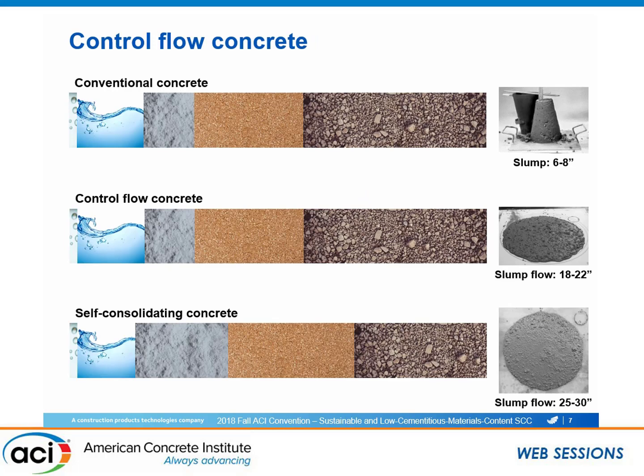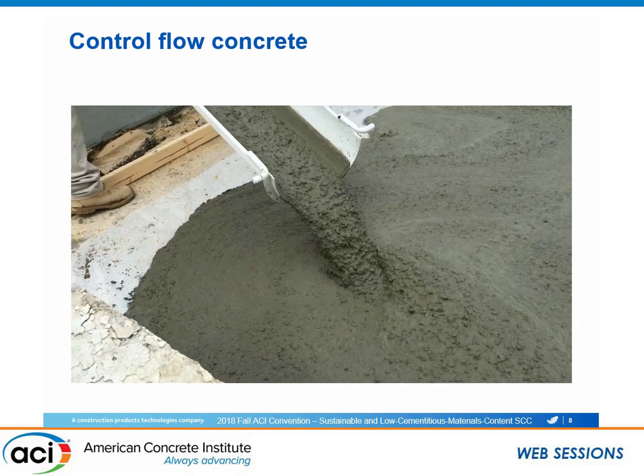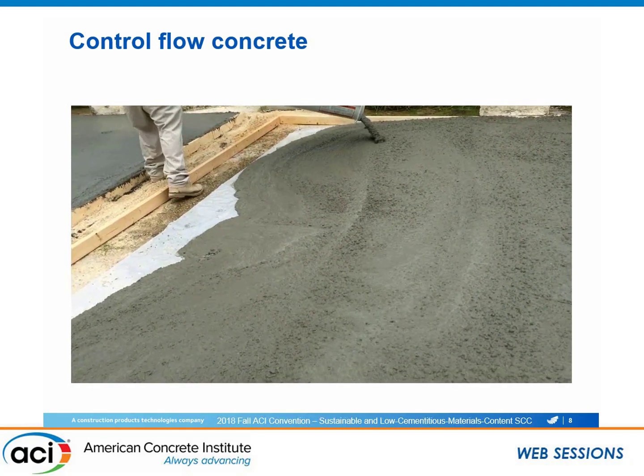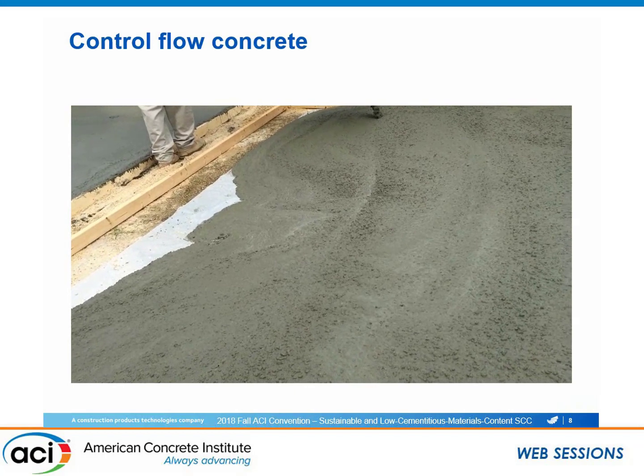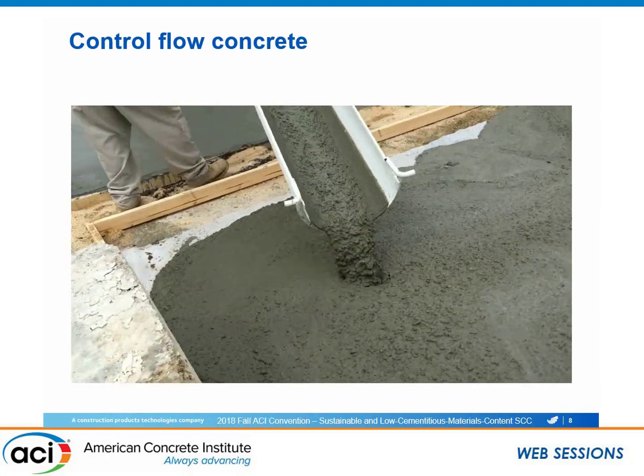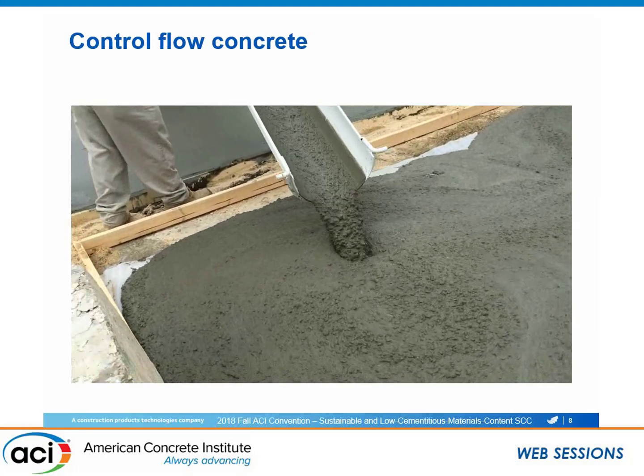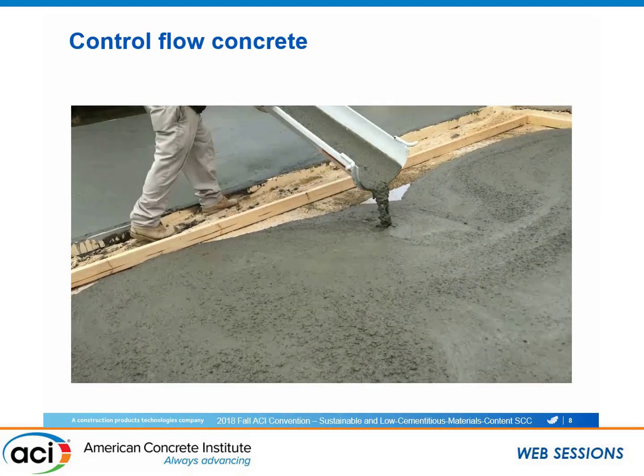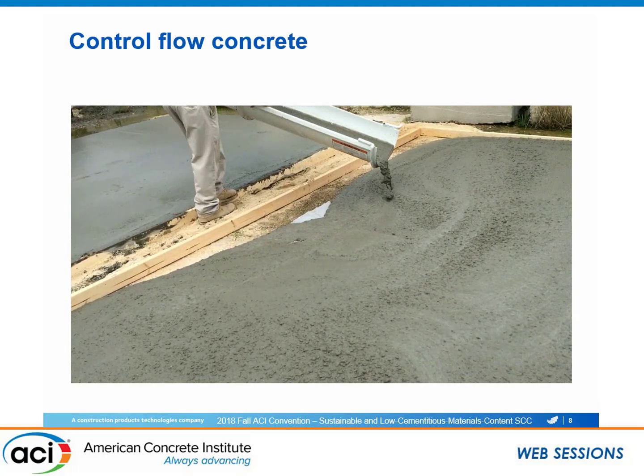The proportions are the same for what we're calling this control flow concrete, but we're still able to achieve quite a large slump flow and meet your segregation resistance requirements. You can see it flows very well — it's not as flowable as SCC, so the edge isn't flowing all the way to the end. But for the formwork shown here, there's a tiny gap underneath, and with SCC sometimes, especially if it's bleeding or starting to segregate, you'll get runoff underneath. With this control flow concrete, you get a nice edge stability so you can maintain the flowability but keep everything in the form.